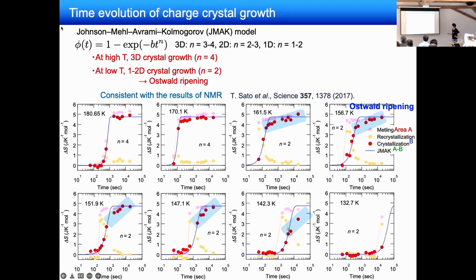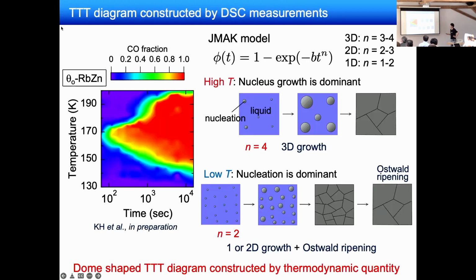And from this time dependence of the entropy change at various temperatures, we constructed a TTT diagram for this rubidium zinc compound. And again, we obtained a dome-shaped TTT diagram. This domed shape indicates that the crystallization progress is given by nucleation and the nucleus growth process.